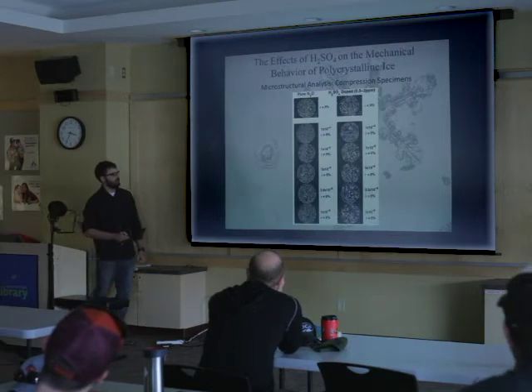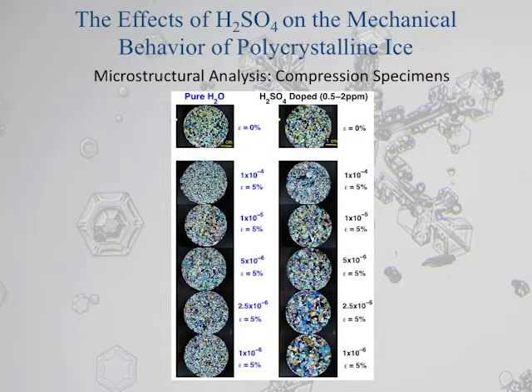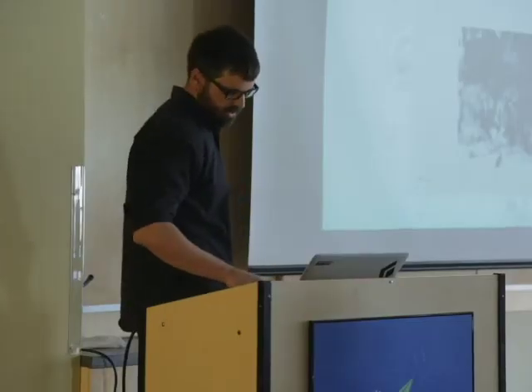It also had an effect on what the microstructure looked like. If we look at these ice grains in the doped sample versus the undoped sample, the grains tended to be much larger, so that was affecting how they grew over time. And it also affected the number of cracks that we saw.